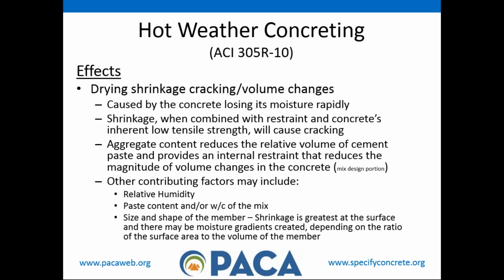Well, the first one obviously is one that everybody sees: cracking, whether it's dry shrinkage cracking or plastic shrinkage cracking. Plastic shrinkage cracks are entirely different than dry shrinkage cracks. I'm going to go over the dry shrinkage cracks first, then work into the plastic. The biggest difference with plastic cracks is they occur while the mix is still plastic, not completely set yet, and typically the cracks for plastic don't go much more than 1/4 to 3/8 of an inch deep.